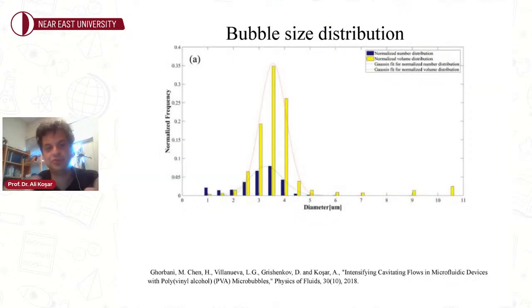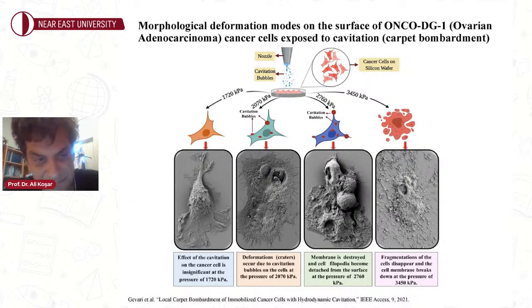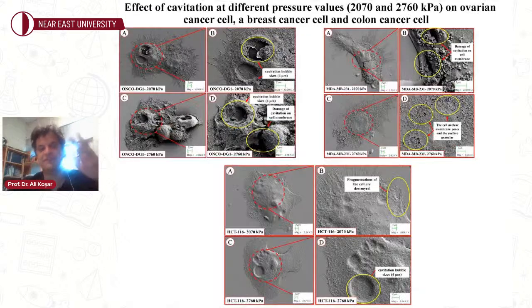And using the visualization system, we can have an idea about the distribution of size of the bubbles. So the average size of the bubbles is 3 microns. So we can clearly see that the bubbles are responsible for creating craters like this. And we can, of course, test many types of single cells, for example, different cells like this. And for example, here you can see 4 different cells, and depending on the cell type, we have different modes of damage.